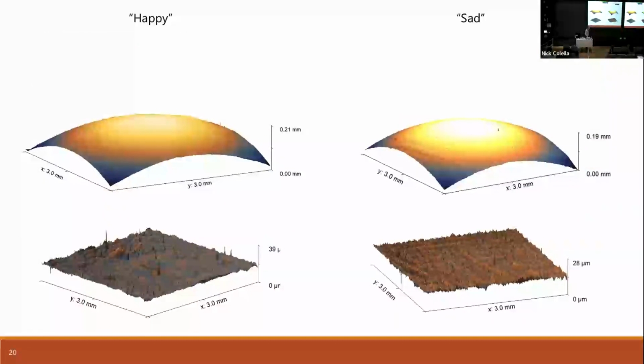So we can do some cool 3D images. This can be great for publications and presentations if you want to impress people with all the data you can collect from a surface, depending on what your material is. We can get some nice 3D representations. And you see that for the curved surface, we can actually start to pull out all that patterning. And for the happy ball, it's pretty smooth still. But we do see those spikes down here.